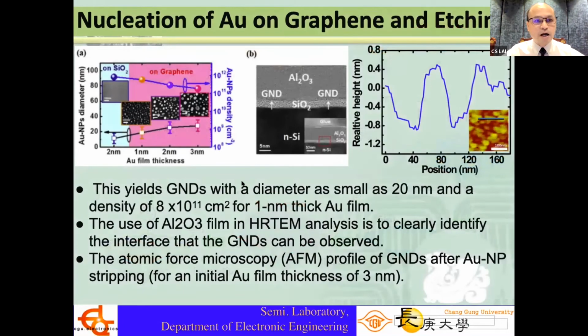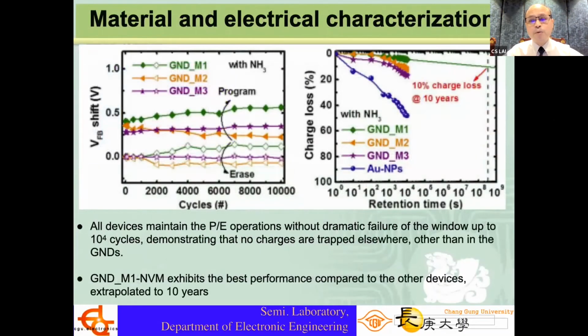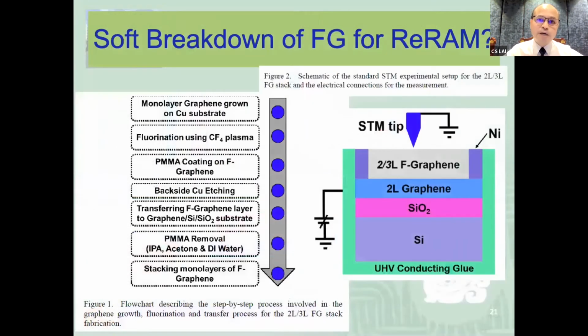As a check, we used SEM to see the scale. The scale is around some tens of nanometers. So we can achieve high performance with very little charge loss. A 10% charge loss can be sustained for 10 years. So after the flash memories, we will check the resistor type memory applications.